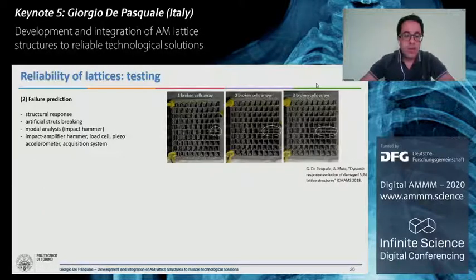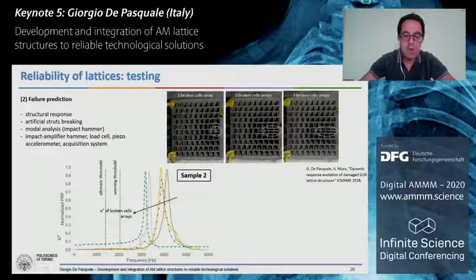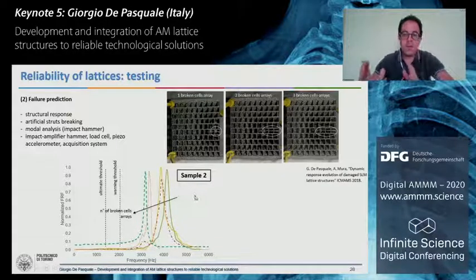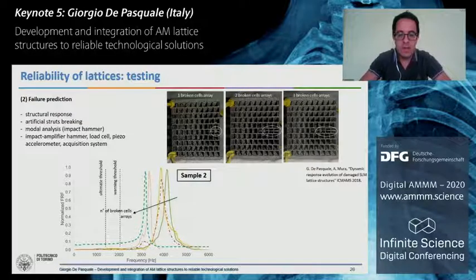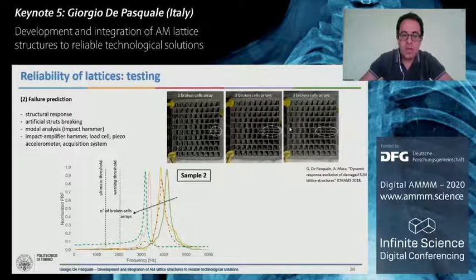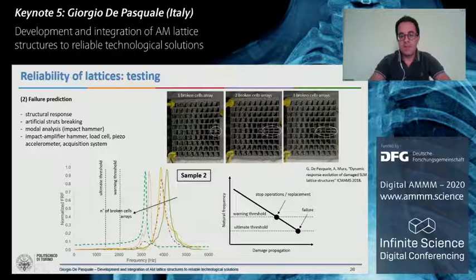Another approach, for example, is to induce some failures on our lattice structures and to modify the global stiffness of the structure. In this case, we can use the structural dynamic response to predict the moment of catastrophic failure. And in fact, if we see the dynamic response of this sample, where we have damaged artificially some rows of cells, of course, we can see that the response varies. The resonance peak is moving. So we can also define a warning threshold and an ultimate breaking threshold that can be considered to replace the structure, or even to stop operations, and even to prevent the failure.